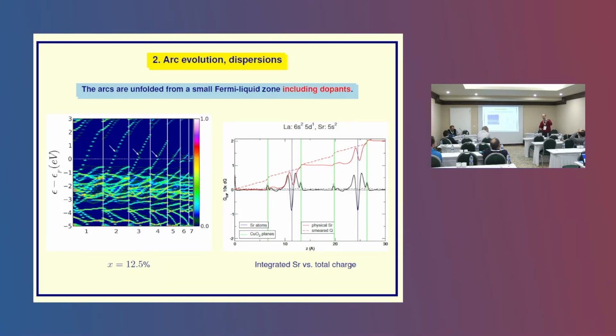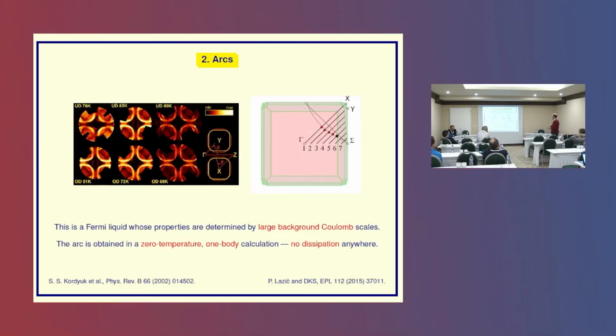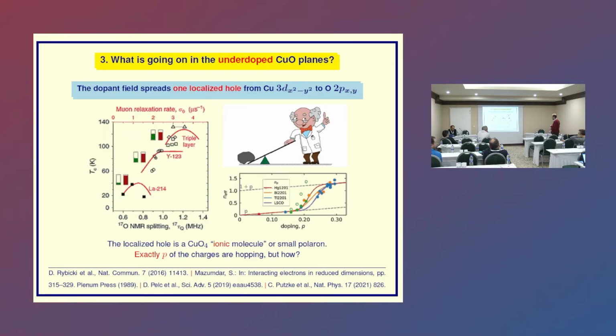In other words, the doping of the planes is actually some kind of Coulomb domino effect propagating through the insulating layers, by which finally the copper exports a hole or part of a hole onto the oxygen. And this partial export of the hole from the copper to the oxygen can be beautifully observed by O17 NMR splitting. It is this Rybicki 2016 Nature Communications paper. Here you see the green is the electron on the copper, and this red is the electron on the oxygen.